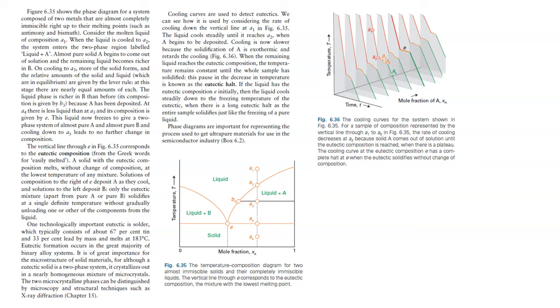Solutions of composition to the right of E deposit A as they cool, and solutions to the left deposit B. Only the eutectic mixture, apart from pure A and B, solidifies at a single definite temperature without gradually unloading one or the other components from the liquid. A technologically important eutectic is solder, which typically consists of about 67% tin and 33% lead by mass and melts at 183 degrees Celsius. Eutectic formation occurs in the great majority of binary alloy systems.